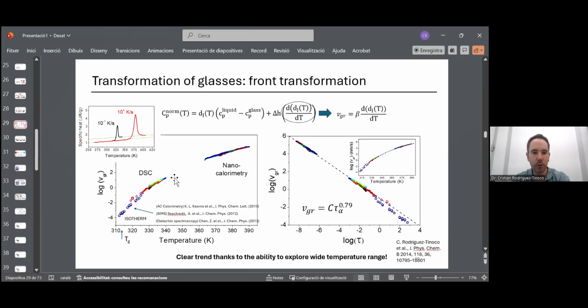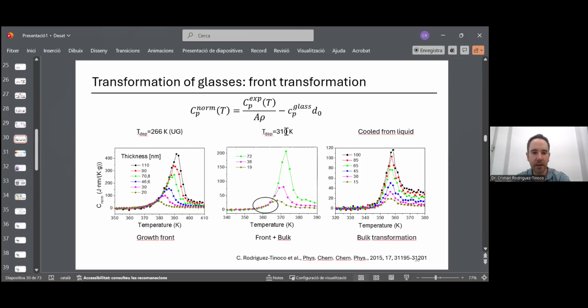Okay, so I will go a little bit faster because of time. But basically, the important thing here is that this protocol can also be applied to a glass which is vapor deposited as well, but it's not as stable as the ultrastable glass. It is deposited at 310 Kelvin, so not the ordinary glass, but also not the ultrastable glass. We do this normalization, and we see some region where these curves collapse into a single curve.